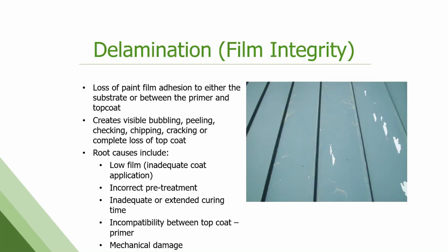The one we see the most of is mechanical damage. And in our world, mechanical damage means any kind of exterior force that has occurred on the surface to cause an opening in the painted surface that then leads to delamination. So scratching during installation or afterwards, fasteners maybe not being done right that tear through the surface, and then now there's a little opening where moisture and ice over time or whatever can get in there and cause that paint to start coming off.